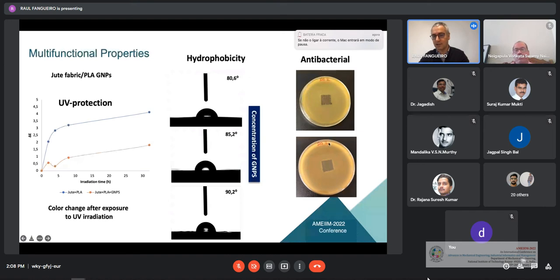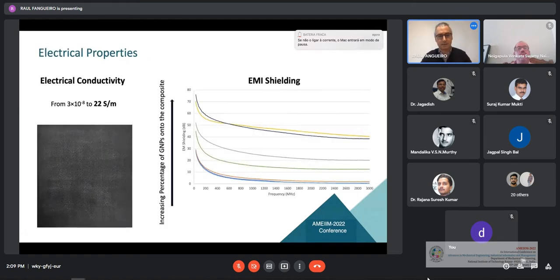You can see here that when we have a functional fabric with these nanoparticles, we don't have bacteria growing on the surface of the material. So we have multifunctionality based on a single functionalization with nanoparticles. We also have high electrical conductivity, and we can use that too. You can see here, when increasing the percentage of graphene nanoparticles in a composite material, we can increase also the electromagnetic shielding of the material itself, which is very important for other applications.